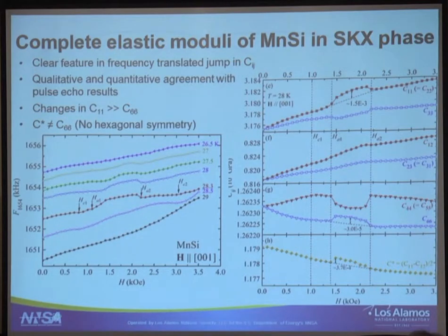The other thing that also tells us is we calculate C star, and as I told you, that's the pure shear in the 111 direction. This is in the 110 direction. These, if we have a hexagonal symmetry, should be the same as the C66. So the jump here is actually an order of magnitude bigger than in the C66. So this is telling us that we do not have a hexagonal symmetry. So the symmetry of the Skyrmions is not winning against the lattice symmetry, at least in terms of elastic modulus.